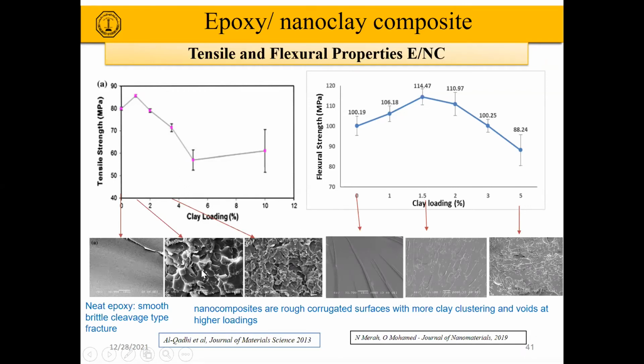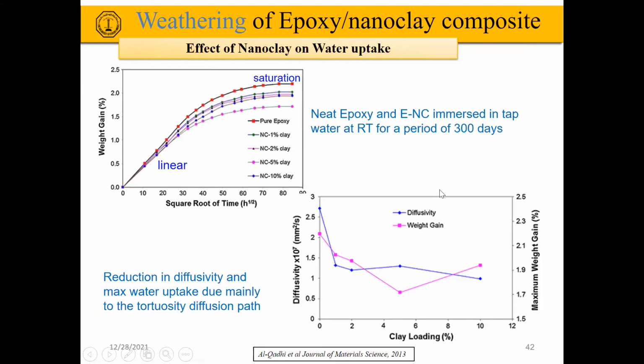If you look at the fracture surfaces, you see that the neat epoxy has a smooth, brittle cleavage type fracture. The nanocomposites have rough and corrugated surfaces. And for 5%, you start seeing voids and clusters of nanoclays. So that is the material that becomes now our new matrix.